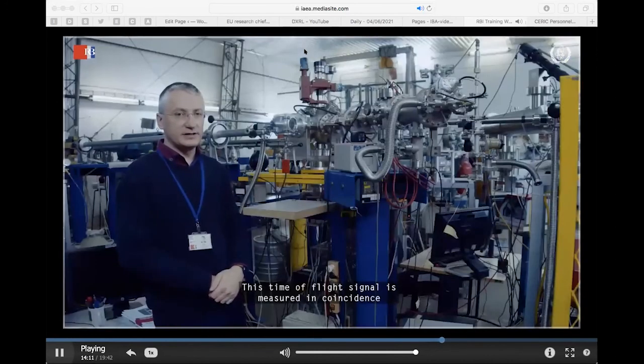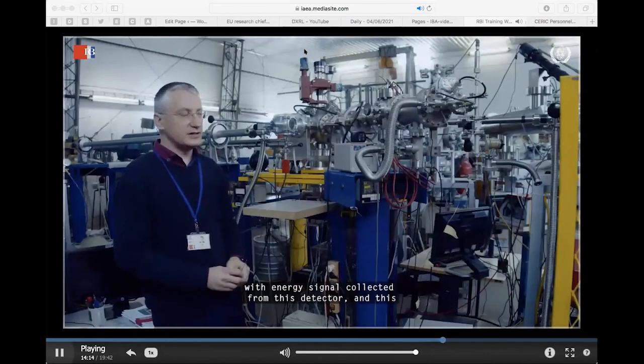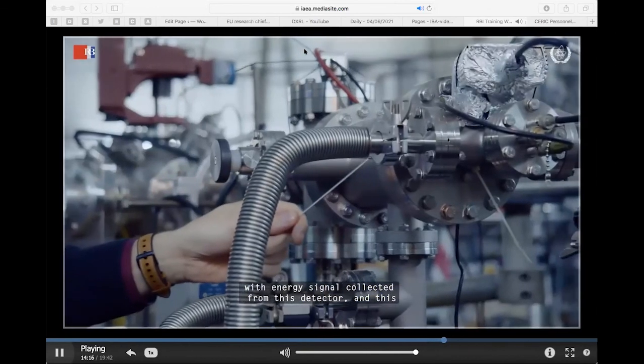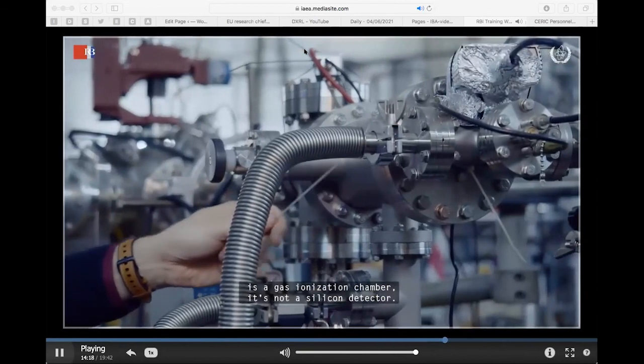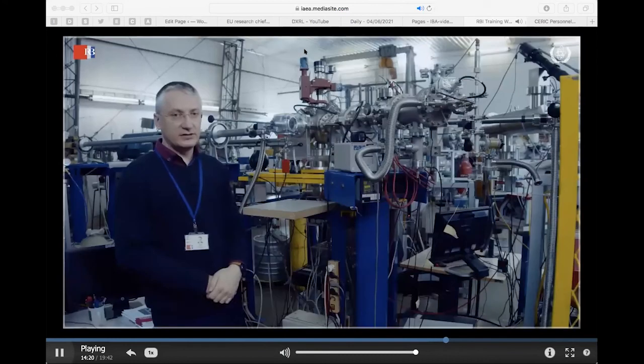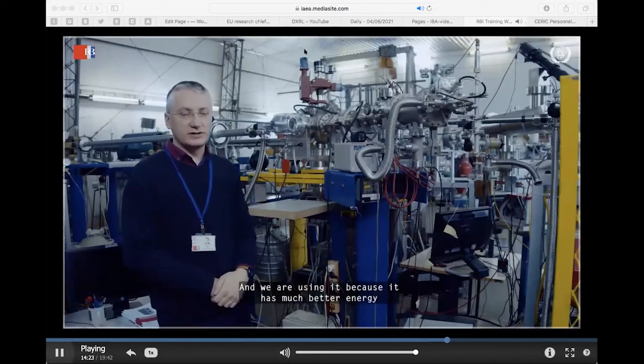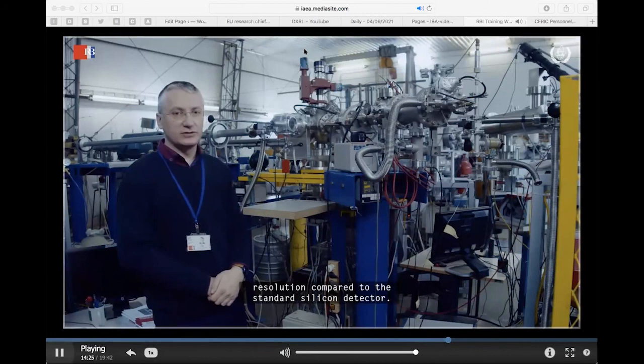This time of flight signal is measured in coincidence with the energy signal collected from this detector, and this is a gas ionization chamber. It's not a silicon detector, and we are using it because it has much better energy resolution compared to the standard silicon detector.